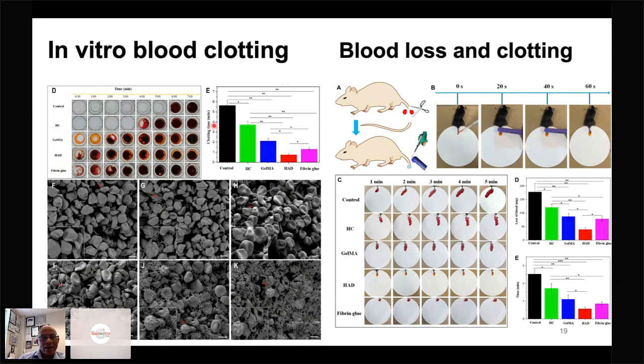And then when we look at the clotting time, this is a control. It took about 5.5 minutes before a clot was formed in the control. That's nothing added. And this is just the reptilase alone, which is the enzyme that is extracted from snake venom. This is GelMA, and this is our material, and this is fibrin glue. So you can see that we were able to reduce the clotting time down to about 45 seconds. If you look at this axis, it's about 45 seconds. So in 45 seconds, blood is turned into a clot, and then therefore it seals the surrounding tissue.